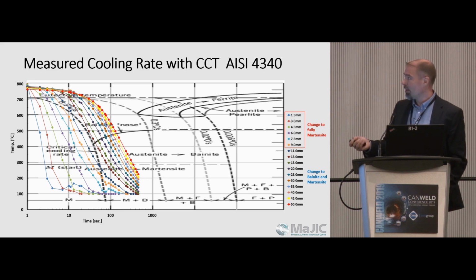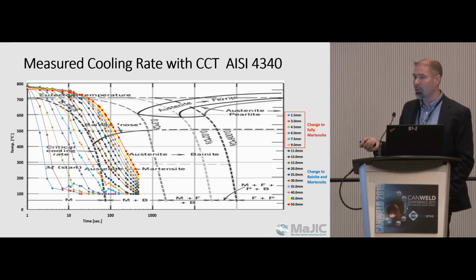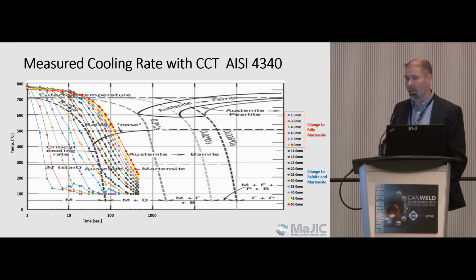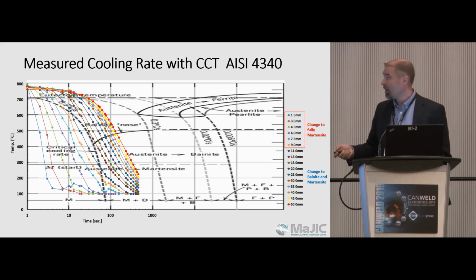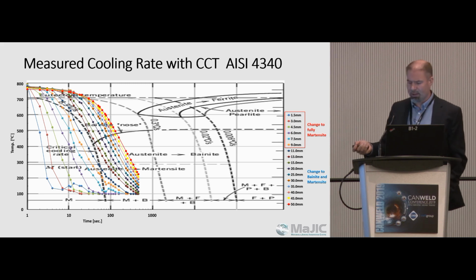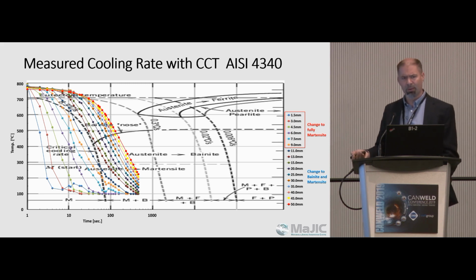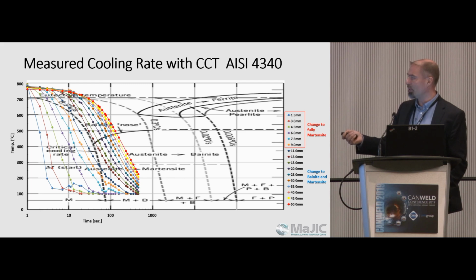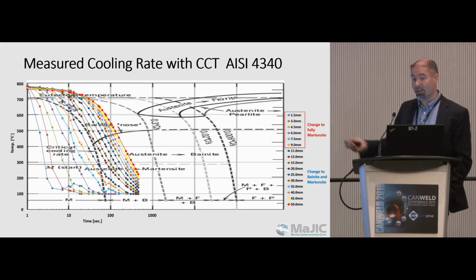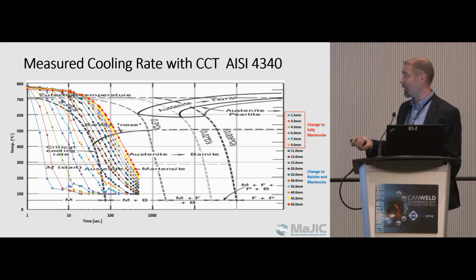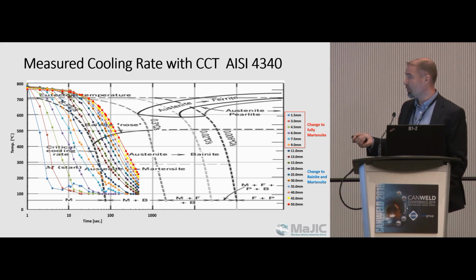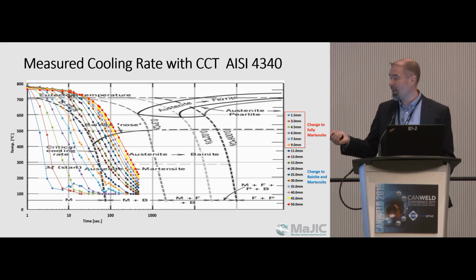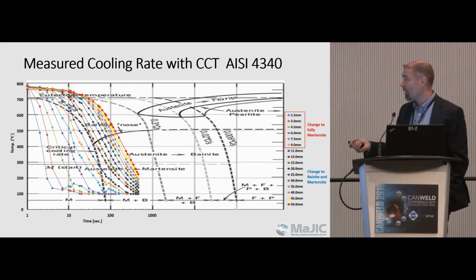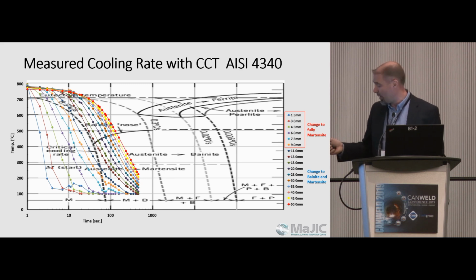So we can see the colored lines, these are the actual measured cooling rates that we see at different distances from the end of the Jominy end quench sample. And we overlay it on the CCT diagram, and lo and behold, we find that things match. So this is a very good sign that we're able to predict, at least according to the CCT diagram, what the microstructure is going to be. So the first 6 indentations on the sample were fully transformed to martensite, and the remainder were changed to a bainite and martensite mix, depending on where in the bainite nose they fell.